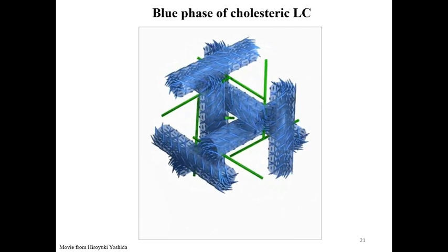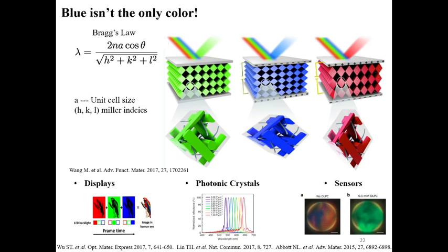liquid crystal. It is very useful because of the lattice parameter a, which is the size of each unit, and which kind of lattice crystalline structure forms. When you have white light in, by changing or tuning the structure of the blue phase, you can selectively reflect just one particular wavelength of light. So overall, you will see the film as blue, red, or other colors.